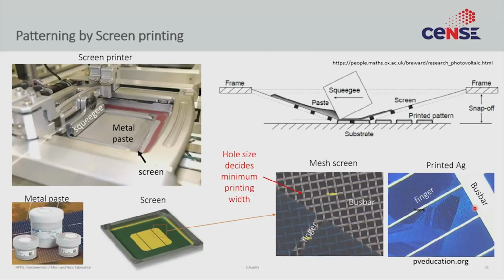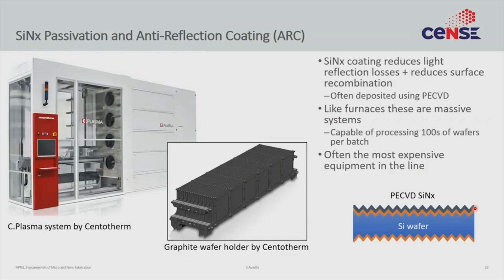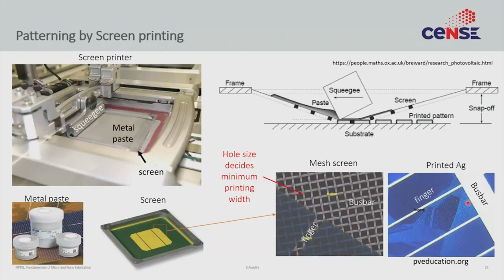So let's get started. In the previous lecture, we had finished PECVD. So this is what the cross section looked like. You had silicon wafer. You have this orange layer, which is the doped phosphorus. The doping is on both sides because you were doing this without any patterning. So there is phosphorus on the back side too. And this phosphorus, as we shall later see, will go away, but for now it's there. And on top of the front surface, we have deposited another layer of PECVD silicon nitride, which is this dark blue color, and that is to reduce reflection of light. Okay. So now we have to deposit metal.